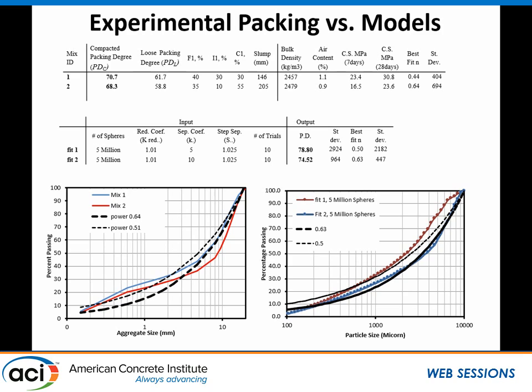But if you compare these two to these two real-world mixtures with 40 and 35% fine aggregate, you get 70 and 68 in the lab. Like I said, it's not very far, but what it shows you, when you compare it to the power curve, is how off you are from the power curve. With fit 1 and fit 2, your best fit would be 0.5 and 0.63, versus in the experiment, your best fit would be 0.44 and 0.64.